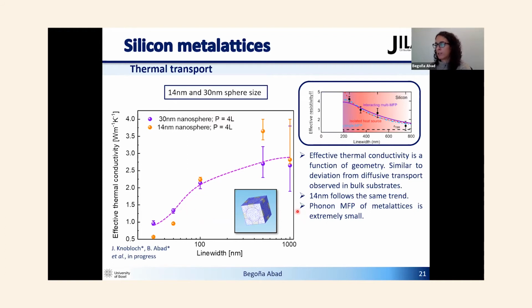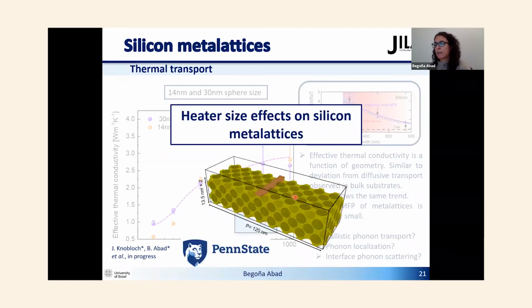So to try to understand this behavior, we are wondering about different phenomena that could be explaining this. We are wondering if this is coming from ballistic phonon transport, from phonon localization, or even from interface phonon scattering. So in order to understand this a bit better, our collaborators at Penn State University are performing molecular dynamics on this type of systems to understand the heat transport effects on these silicon metalattices.